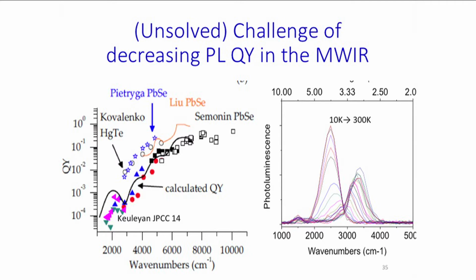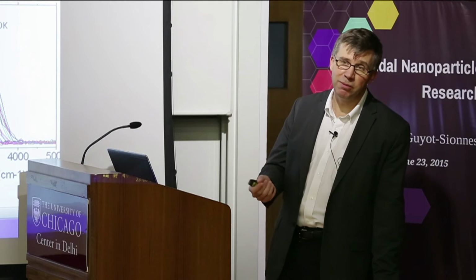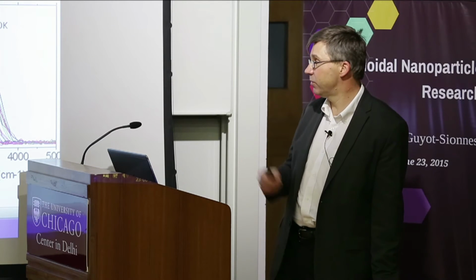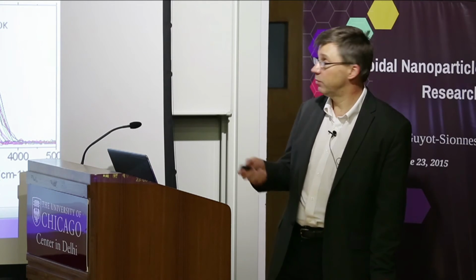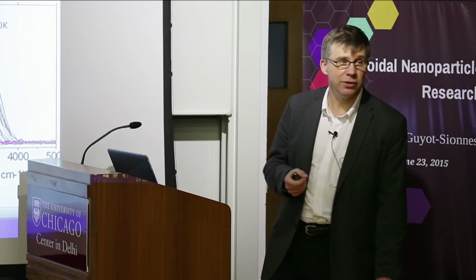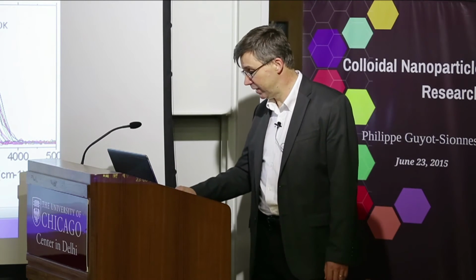Oh, so we say there are traps or something. We always attribute changes in luminescence to traps. But this case is not. In this case, the change of luminescence is due to energy transfer to the vibrations of the ligand on the surface of the particle. And it's happening exactly where those vibrations are, the CH vibration. And so we're facing the same problem that organic molecules have, except not to such a drastic extent, because we still see some luminescence. But eventually we'll have to solve that problem.